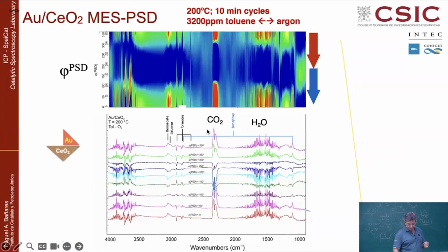And with gold ceria, it's very fast. It's a crazy burning system. So immediately you get a lot of water, and this is not environmental water. It's water that is being formed or consumed, positive or negative, during the reaction. So as you see, a lot of CO2 and water form, because this is formed from the reaction. Then you no longer feed toluene and you feed the oxygen, and the production of water and CO2 decreases and then increases. But you still see a little bit of bands of formates and other molecules which are being formed, or even the benzyl oxide. The first molecule is formed and very quickly consumed. So you get a lot of insight into the reaction mechanism.